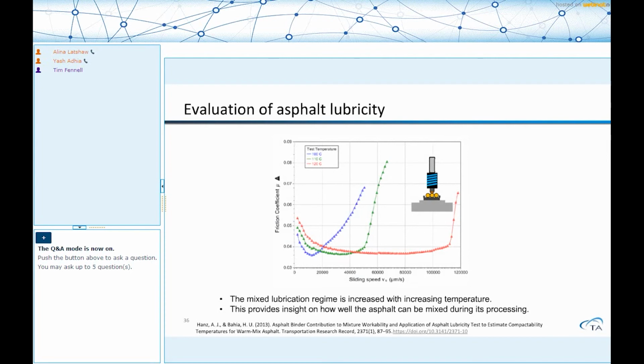This is where, when you look at warm mix asphalt technology, or hot mix technology, a big amount of effort is driven to improve the processability of asphalt while laying it down on the road without having to heat it up too much. I won't go into the whole lot of details about the exact mechanism. The paper that I've cited over here is a very good reference that goes into the details at the molecular level. What I do want to show is that it has been shown that friction plays a lot more important role than one would envision in terms of understanding why warm mix asphalts behave the way they do and how you can use these measurements as the overall mixed lubrication regime starts increasing.